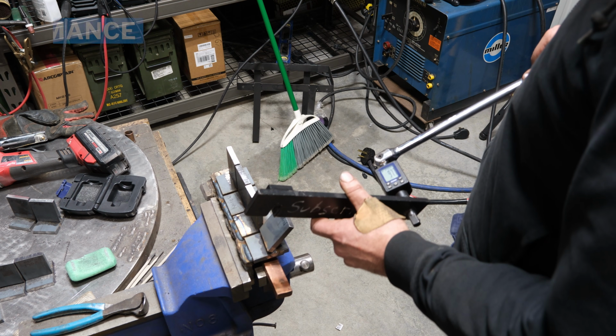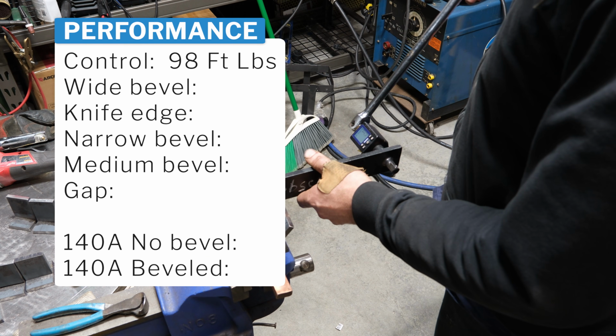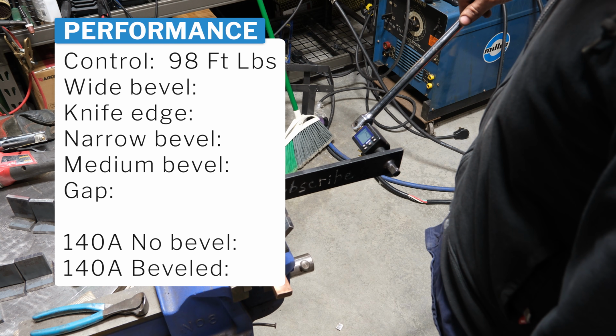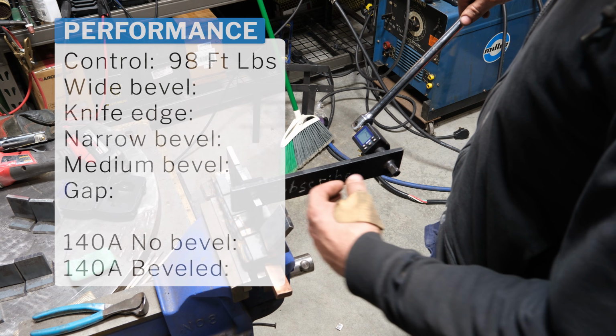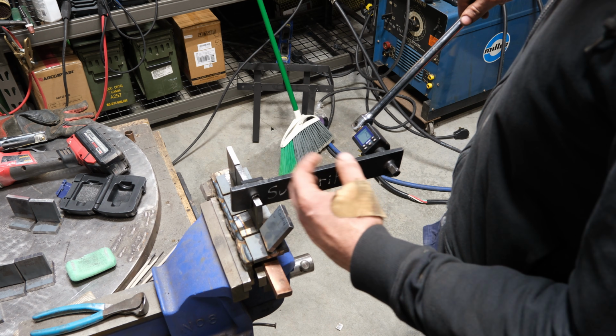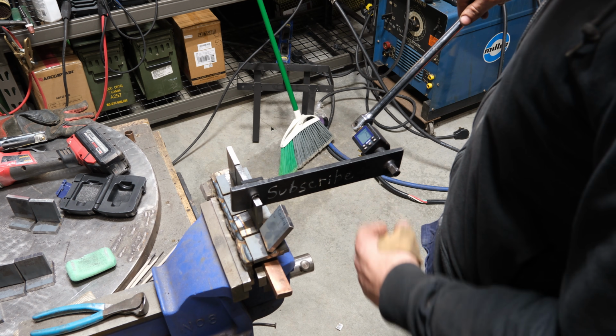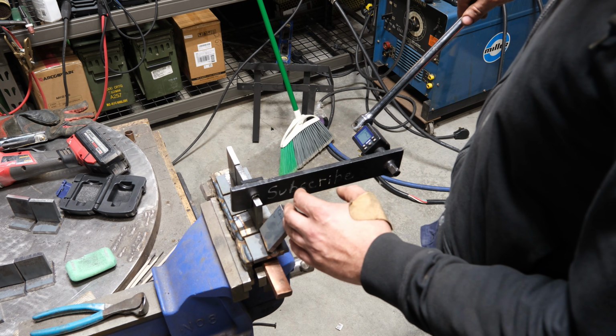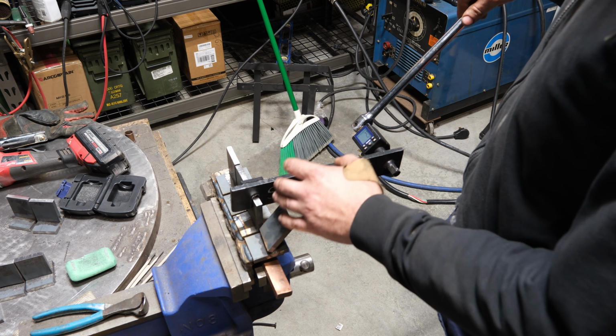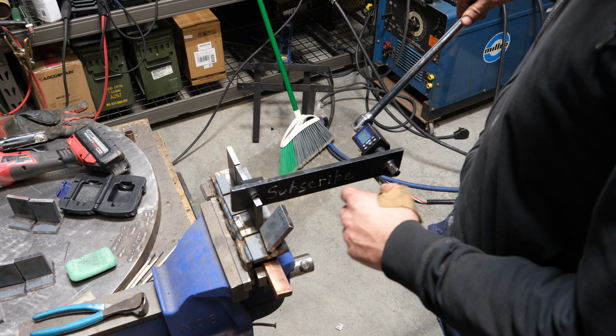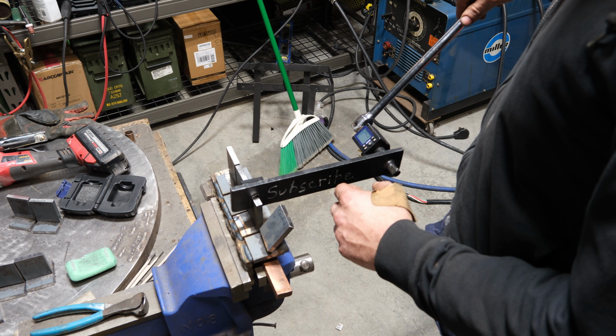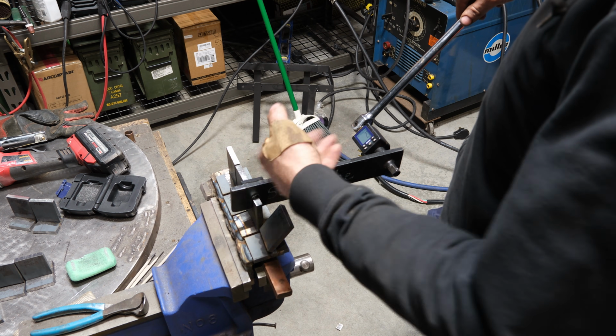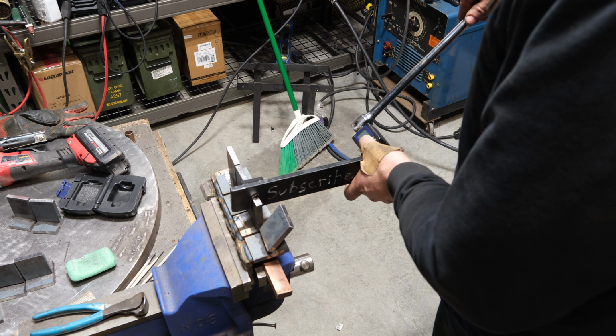97.7, pretty typical, and we don't have much root fusion due to all of these being done with the short arc process. With multiple passes, it would be higher, but again, we're comparing single passes. And the main purpose of this isn't so much to compare the results here, it's to look at the penetration inside of the weld is really what we're here for. But I'll throw this in so we all have an idea.